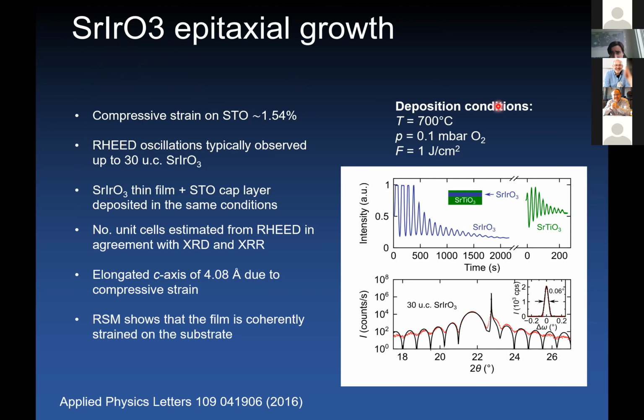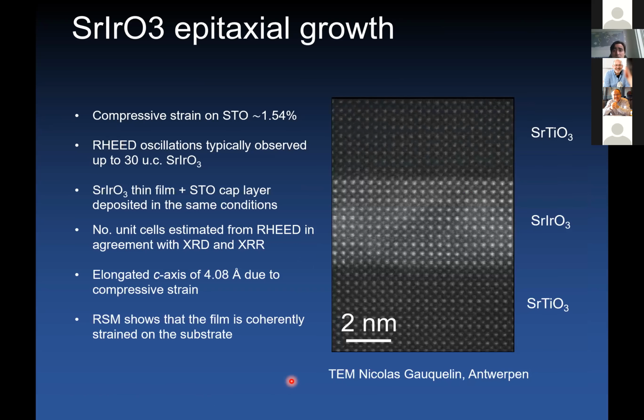So using these particular conditions, you can have very sustained RHEED oscillations during the growth of these systems. And as I will explain later, we always cap our film also with an epitaxial layer of strontium titanate to essentially protect these films. And these films are coherently strained to the substrate in a compressive strained state. So this is a TEM image of one of these iridate heterostructures with the strontium titanate substrate and a capping layer of strontium titanate again.